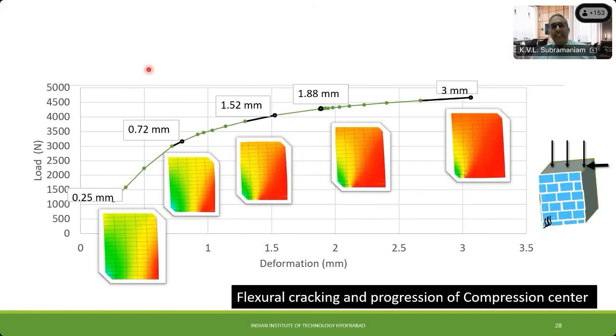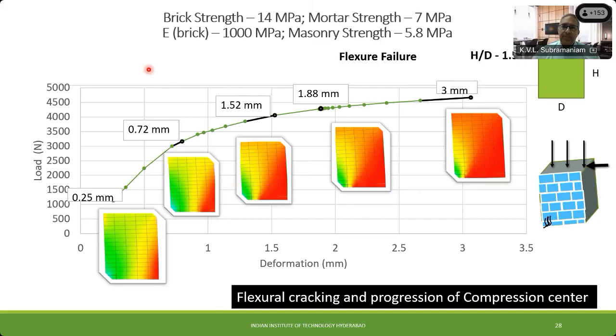Similarly, we can also predict the flexural cracking response of the same masonry. What do I mean by saying flexural cracking? If I take the same masonry wall, which is subjected to 0.3 megapascal compressive stress, but now my H over D ratio is 1.5. So basically now it's getting taller compared to its width, and apply the lateral force, we see that the failure pattern changes completely. Now, this particular wall fails in a flexural mode. The final mode of failure is by crushing a brick at its toe, which is basically the far end from where I apply the lateral load.